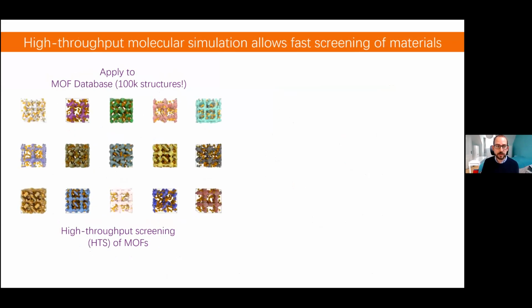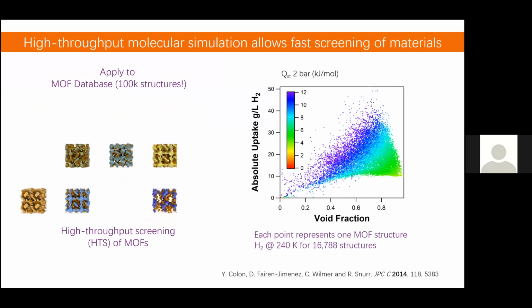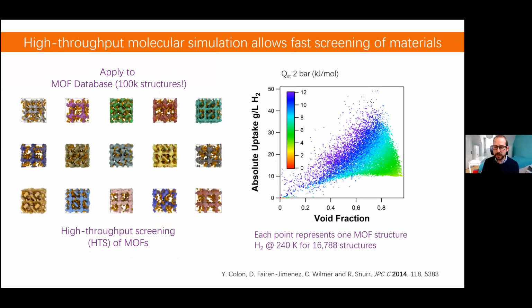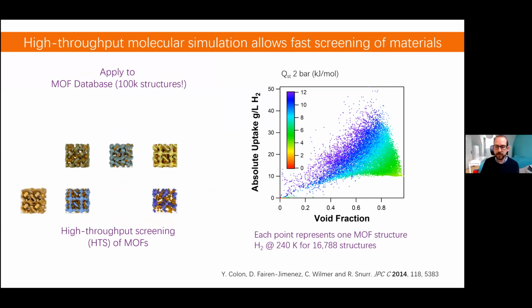Once we have been able to do that, we can start applying this to a database of materials, and we can get something similar to what I have represented here on the right. What is this? This is 16,000 different metal organic frameworks represented in one single figure. Every single point is one single structure, one single metal organic framework, one single Monte Carlo simulation. We can see the amount of hydrogen that we are adsorbing, grams of hydrogen per liter of metal organic framework, as a function of the void fraction of the material, so how porous the material is.